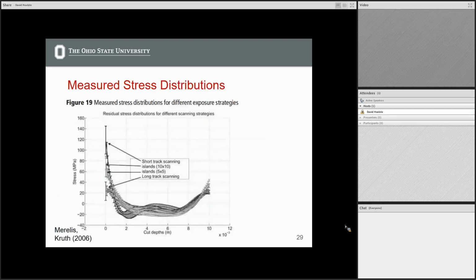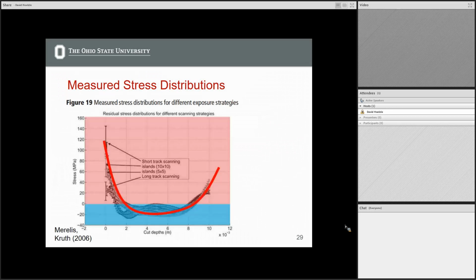So these are their experimental results that they got here. Just trying to highlight the major trends and compare those to the theoretical with this dark red line. We can see that we have roughly the same trends where we have a broad compressive zone in the middle of the part, and then on the ends we have two zones of high tensile stress.